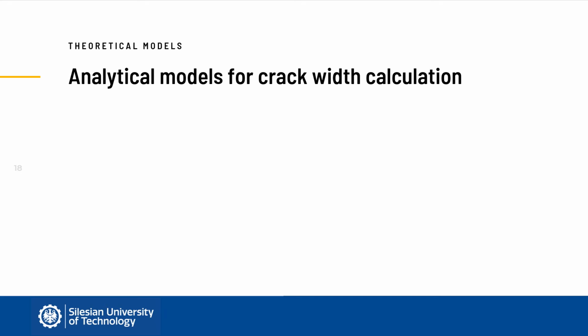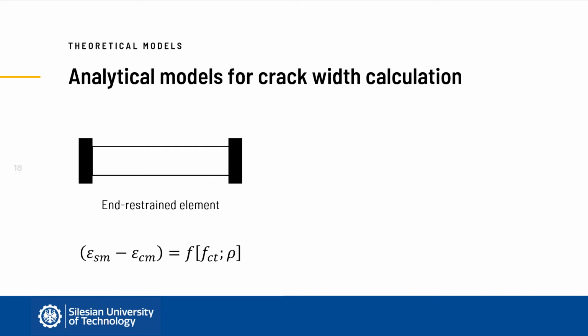The analytical approaches also provide guidance on how to determine the value of the crack-inducing strain. Usually, two representative cases are distinguished. The first scenario is that of an element restrained at its ends. Since cracking in such an element changes forces globally, the crack-inducing strain is dependent on the degree of the applied reinforcement. In the methods, this strain is usually a function of the degree of reinforcement and tensile strength.